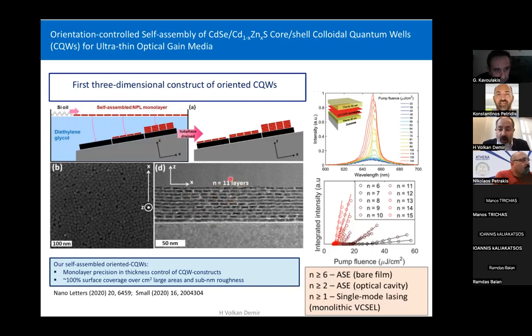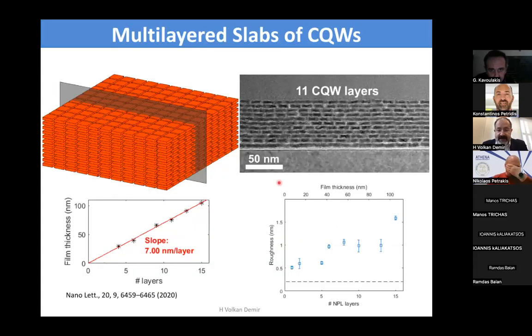And what we observed and the maximum we got was 15 layers. One can actually build up this type of face-down slabs of the colloidal quantum wells. And this was interesting for us because we would like to understand the gain behavior as we build up these structures. In a construct like this, we observe there is a sudden jump with which we observe gain. And that was important for us to explore because eventually we'd like to make them thinner and thinner if possible, and yet still induce gain.